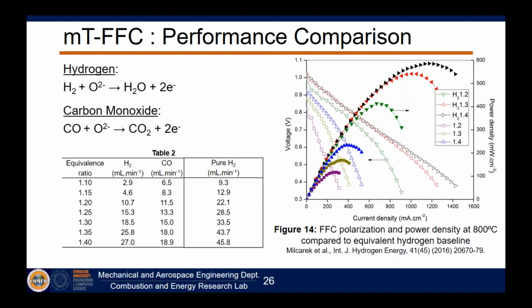What you find is that the equivalent hydrogen potential, essentially, of an equivalence ratio of 1.2, 1.3, and 1.4 is, of course, significantly higher than the combustion exhaust. But what we found, surprisingly, is even though you only have less than 20% syngas within the combustion exhaust, you can actually generate about 33% of the hydrogen baseline. So it's actually possible to generate more power than you would expect from this diluted fuel. So actually, having a diluted combustion exhaust isn't as big of a disadvantage as you might otherwise expect when you compare to pure hydrogen.